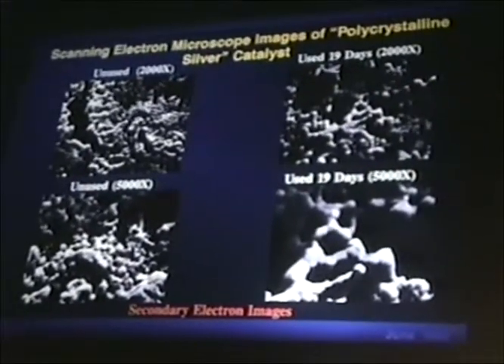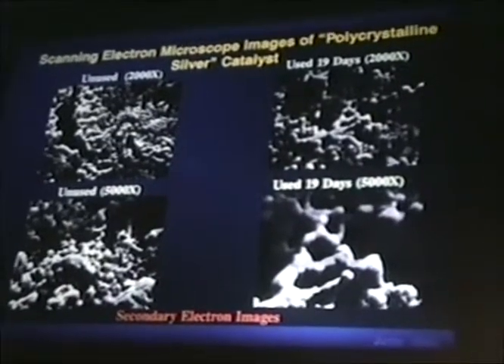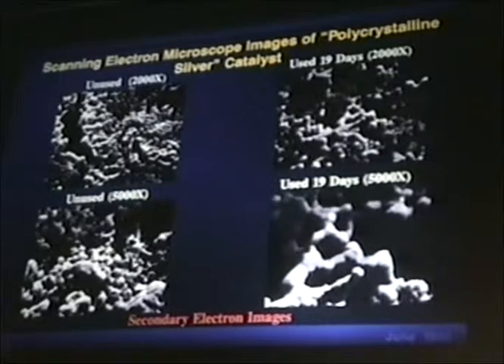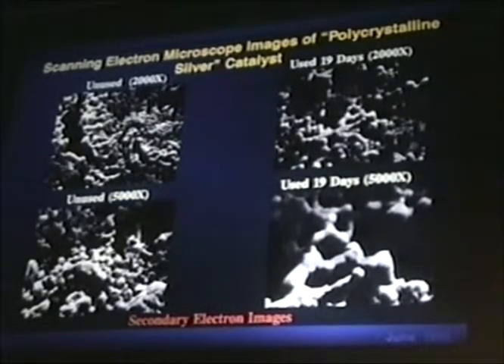Further surface science investigation by scanning Auger microprobe revealed that the high efficiency, and that's the punchline, of this catalyst is due to sodium promoter in a very well dispersed state, and which becomes aggregated upon use. Next one. Next one is just the SEM pictures of both the fresh and the used. And really, there are very low feature differences. I've shown you two significantly different SEM photomicrographs, but essentially there is no difference. It's quite typical of a polycrystalline silver.